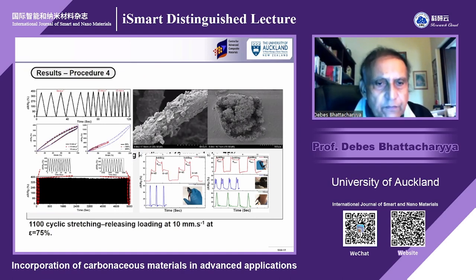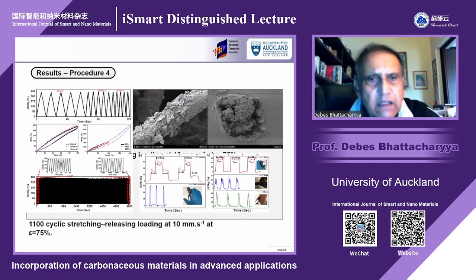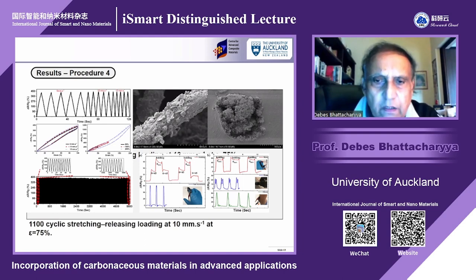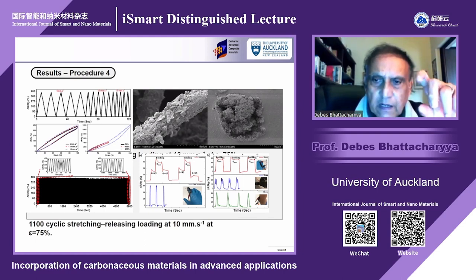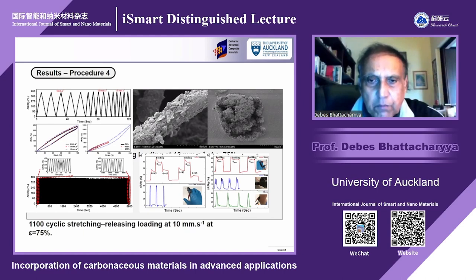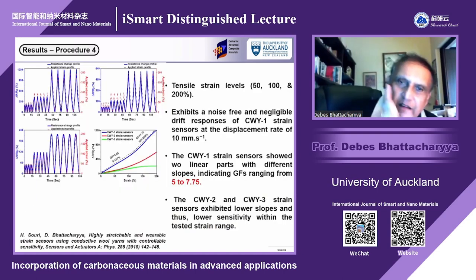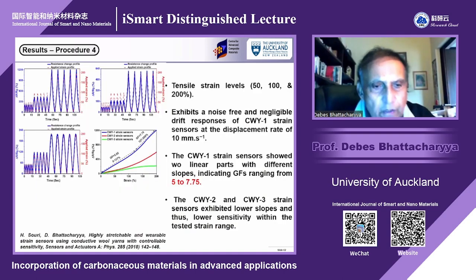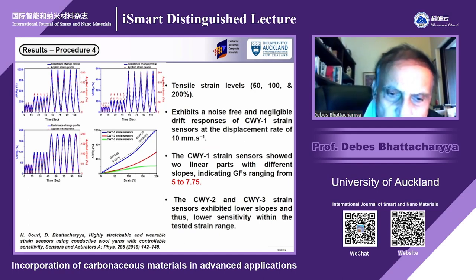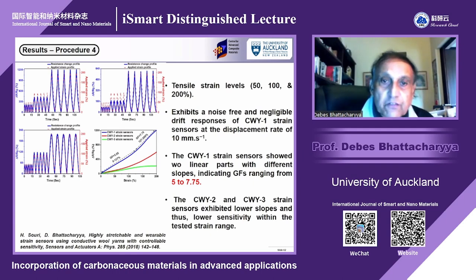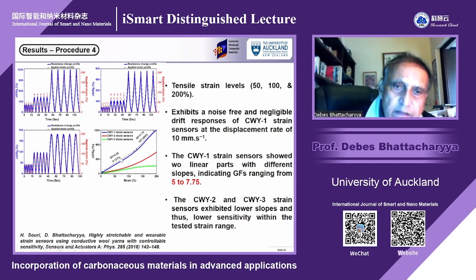Got the results, and if you see that result, it is depositing all right, no problem there. It is responding. If you use the finger responses, you see the blue glove is there, and there we have responses. But important thing, when you plot that, we also published this in Sensors and Actuators A 2018, that if you have the straight one, then the gauge factor can improve from 5, and then there are two regimes. Then in the second regime, it can go close to 8.